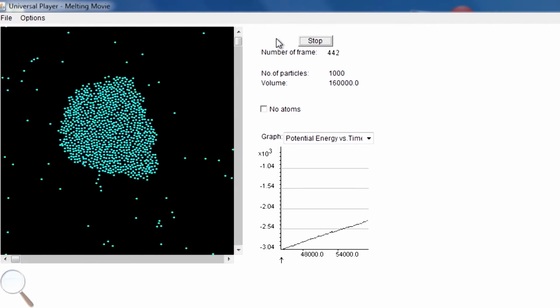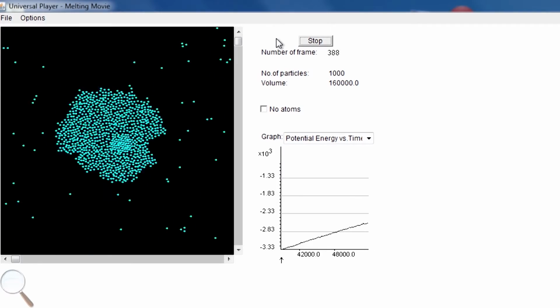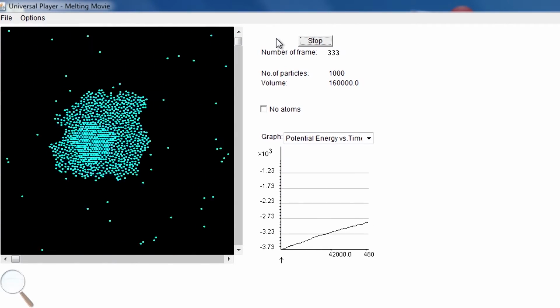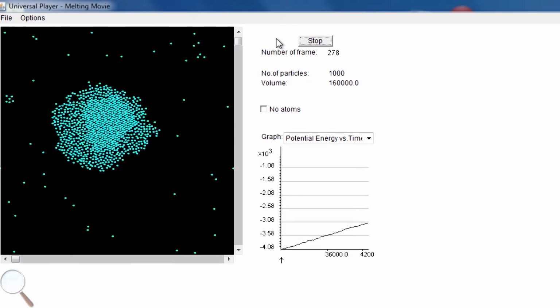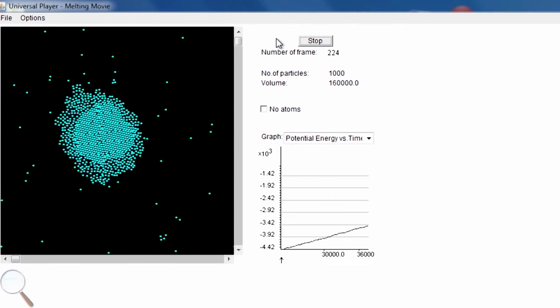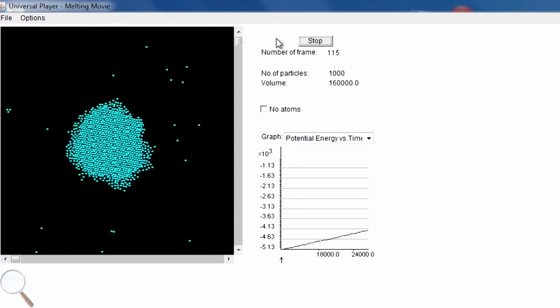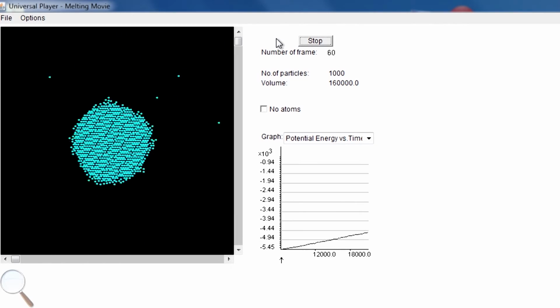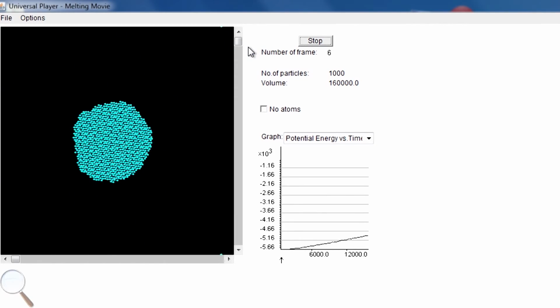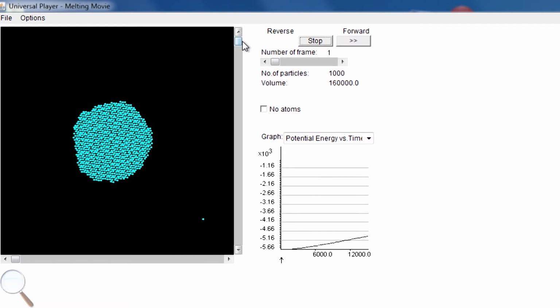If you look at this case, now you have seen the melting transition going all the way back into the solid phase. If you plot a curve between temperature and potential energy, what you will see is that there will be certain parts between the liquid, solid and gaseous phase that are disjointed, and there is a jump, and those jumps are indicative of the changes in potential energy leading to the phase transition. So, these two phenomena, melting as well as freezing transitions, show you that in a given ensemble situation you can